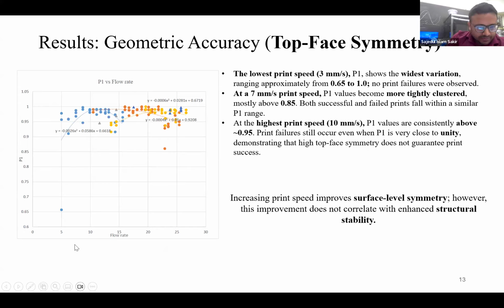If you see the curve, it is flow rate versus the top face symmetry parameter P1, and flow rate basically comes from the print speed. We printed it for three print speeds: 3, 7, and 10. For 3 millimeter per second, the blue one, it is from 0.65 to 1, and it varies very wildly here. At this flow rate, no print failures were observed. But when we increase it to 7 millimeter per second, the flow rate changes, and you see here it is from 0.85, the orange dot.